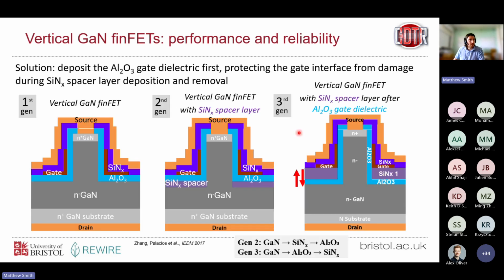So what we did was introduce this third generation device where we try and get the best of both worlds. So now we've still got our spacer layer, it's still present, but the order of our aluminium oxide gate dielectric and our spacer layer has been flipped. So now we deposit our gate dielectric first, then deposit our spacer layer, and then etch it back. So during that silicon nitride spacer layer deposition and etch back process, the sidewall of the fin is protected by the aluminium oxide gate dielectric layer.